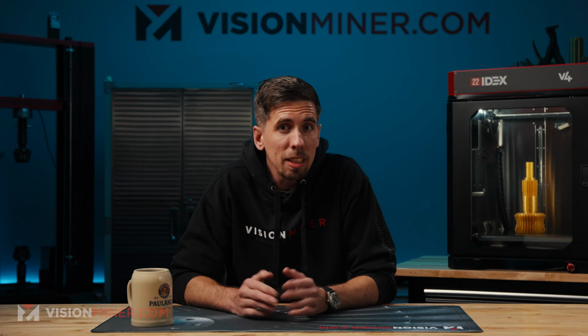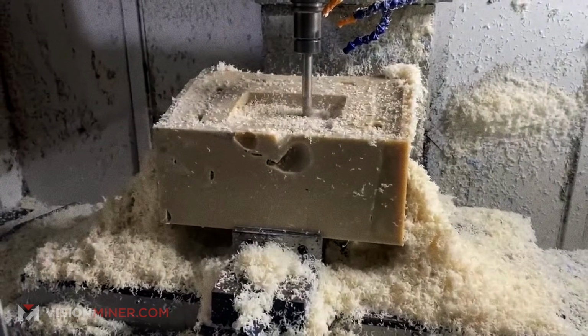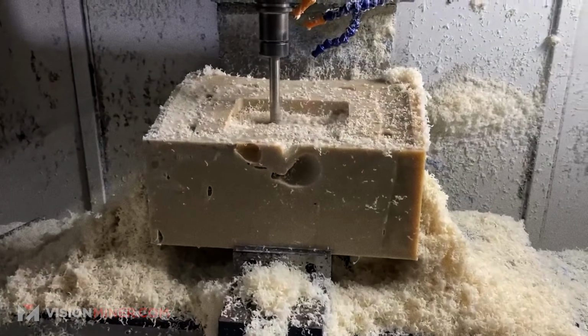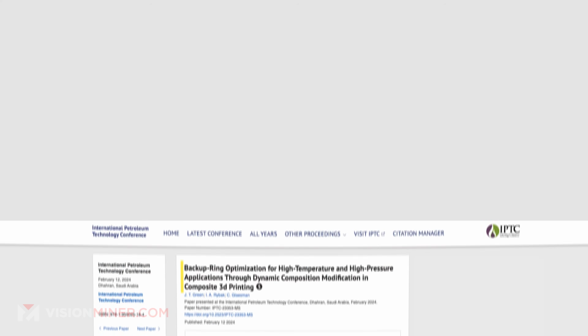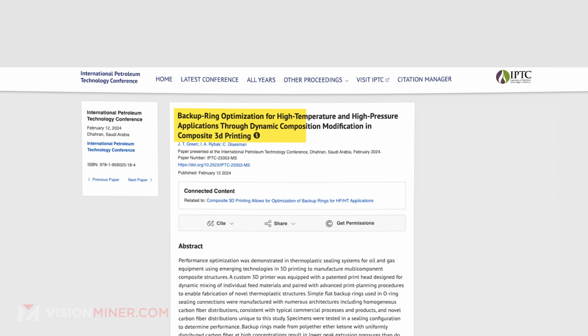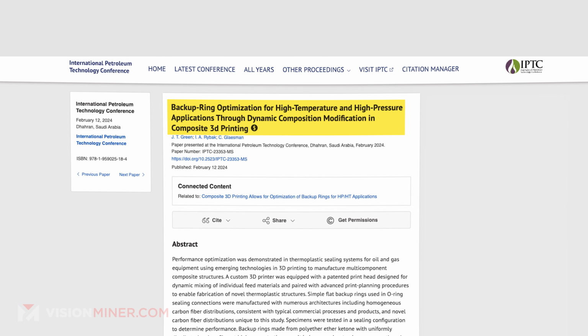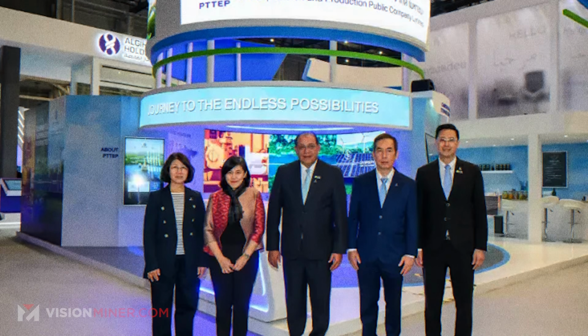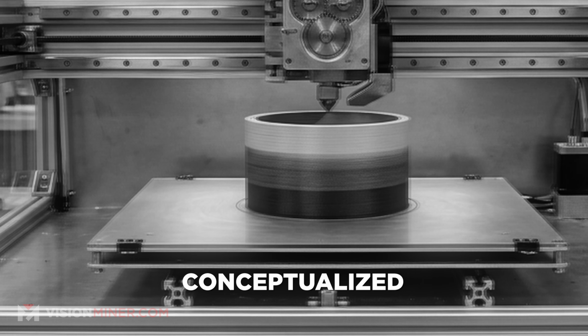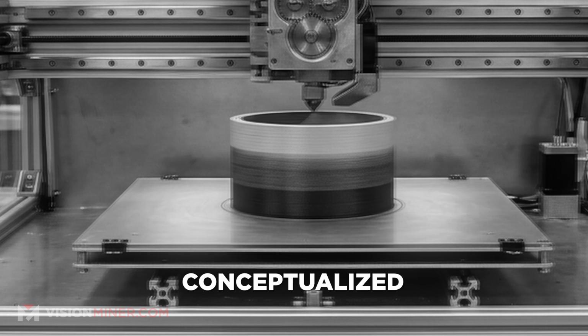The catch? PEEK billet is expensive. Lead times can run up to 16 weeks or more, and every ring you machine wastes most of that stock material as chips that fall on the shop floor. Now, researchers at UTEP published a paper at IPTC, the International Petroleum Technology Conference, in early 2024, co-authored with engineers at Halliburton. They built a custom FDM machine with a patented dynamic mixing hot end, blending carbon fiber content within a single PEEK ring as it printed.